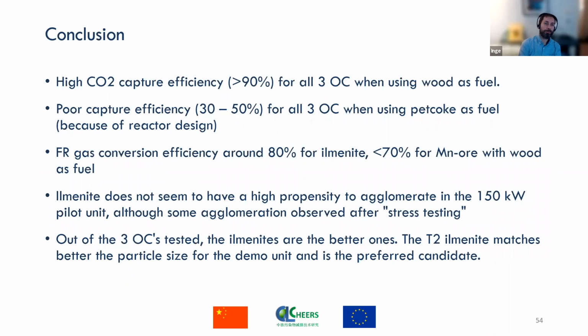Okay, so to sum up, high capture efficiencies, above 90%, were achieved for all three oxygen carriers when using wood as fuel, but poor capture efficiency, 30 to 50%, for all three candidates when using petcoke as fuel. But that is because our reactor design has a low residence time and is not a carbon stripper.